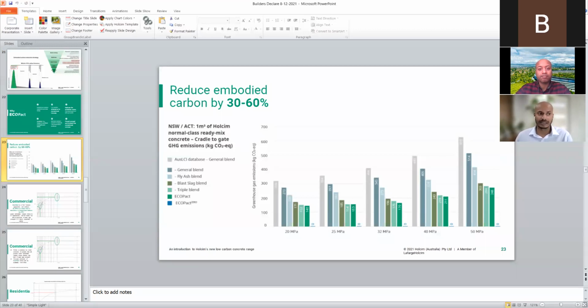EcoPact takes that, and using our internal science, our internal experience, with what we've done with sustainable concrete, we've taken that even further as much as possible. Once that embodied carbon is reduced as much as possible within that 30 to 60%, depending on the strength grade and application, any remaining carbon, we partner with Climate Active and provide those carbon offsets to take it down to zero.